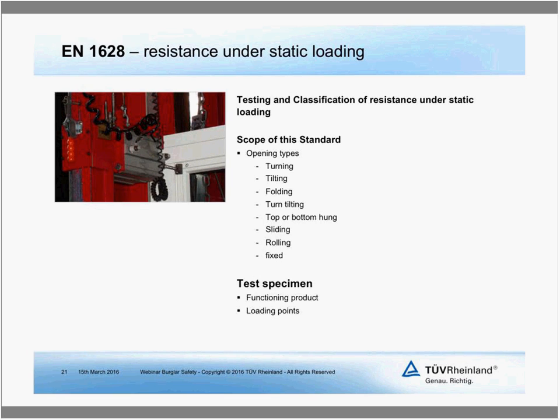If you use glass in this test, the glass pane offering the highest security level shall be positioned on the attack side of the sample. For the lower resistance classes, the glass itself is not attacked. And for higher classes, it certainly will be. But the highest security level should be positioned on the outside, the attack side of your sample. This is also done at room temperature, ambient temperatures. The differences are described in the standards. So normal room temperature is sufficient for your test here.